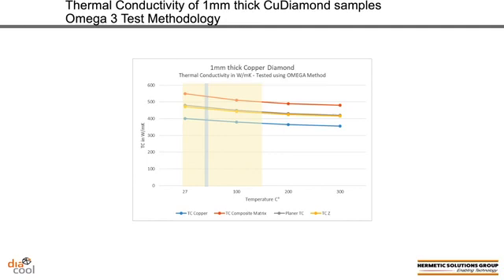Now, interestingly enough, the orange bar that you see on the top represents the matrix itself, that copper diamond matrix, essentially scrubbing away the copper that exists on both sides of the matrix and looking just at the matrix itself. And you can see the effect that the diamond has on that copper, showing us that the material has thermal conductivity up to 550 watt per meter K at room temperature, down to roughly 500 watt per meter K at 150 degrees C.